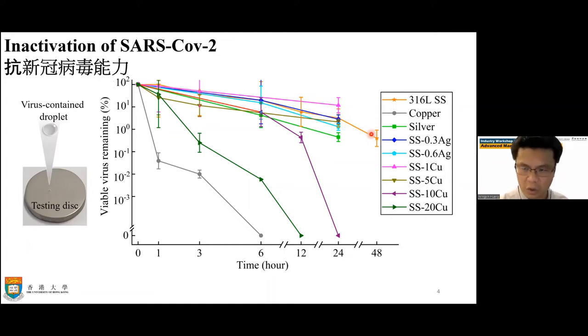Because copper and silver are known for antibacterial properties, and antibacterial is very different from antivirus, we also tried pure copper and pure silver. At the very beginning we thought pure silver might also be used as an antivirus, because pure silver is good for antibacterial. But our results show that silver is not much better than stainless steel. In other words, silver itself is not working for antivirus properties.